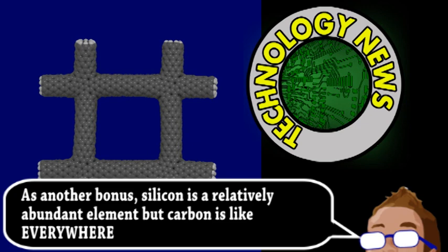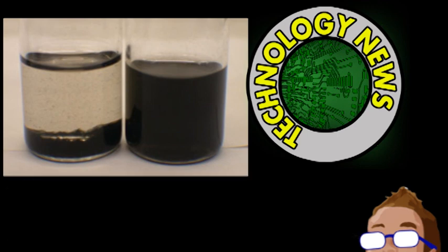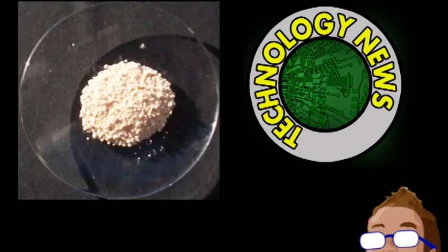Basically, the carbon nanotubes are made water-soluble with a surfactant, also known as a soap. The substrate is mainly silicon oxide with tiny channels of chemically modified hafnium oxide. This gets dipped into the carbon solution, and the nanotubes chemically bond to the hafnium oxide, creating the circuit.